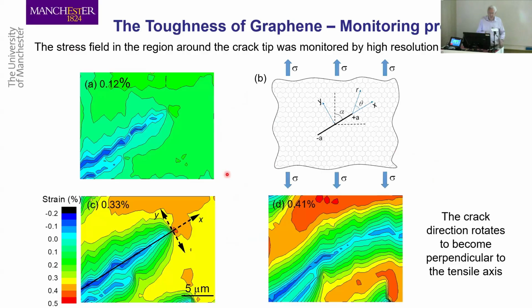So this is now zoomed in to the data points around the original crack. Blue is undeformed, green is deformed. You can see a stress concentration at the tip of the crack. This is the orientation of the graphene lattice and the geometry of the setup. We then increase the strain, and the stress concentration builds up, and you can see a stress concentration sitting at the tip of the crack here. And then when we go to 0.41% strain, the crack grows, propagates, and changes direction, becomes perpendicular to the tensile axis. So we can actually do fracture mechanics on a monolayer of atoms, which is really quite exciting.